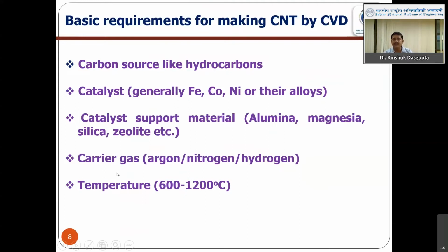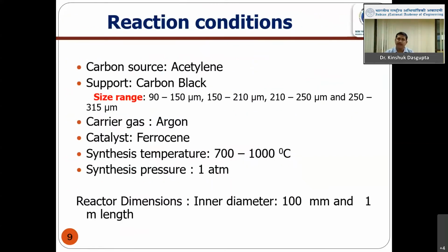We require a carrier gas like hydrogen, nitrogen or argon to dilute the hydrocarbon. Otherwise what will happen, the hydrocarbon, if their partial pressure is high, they will simply crack and give you the soot kind of thing, which we don't want. Also temperature is required to give the required activation energy for the growth of the carbon nanotube. So what we are using as carbon source, hydrocarbon, we use acetylene, which is commonly available and cheap. As support material, we use carbon black. There is a beauty of carbon black, which I will discuss in the next slide.